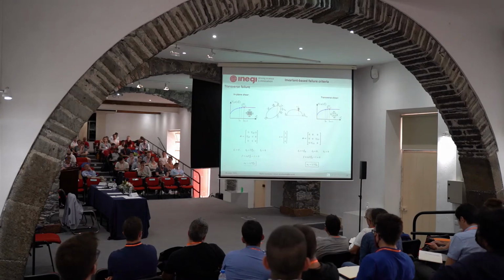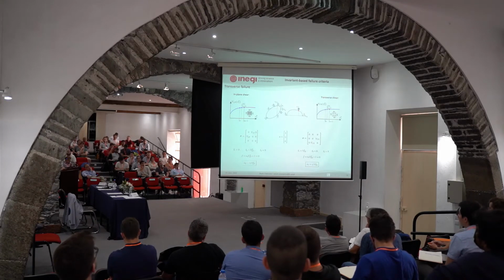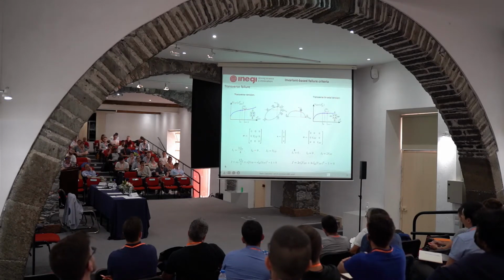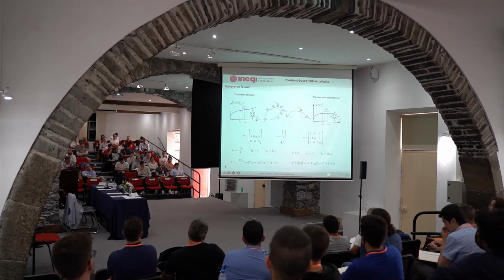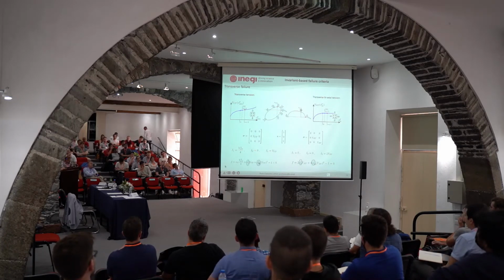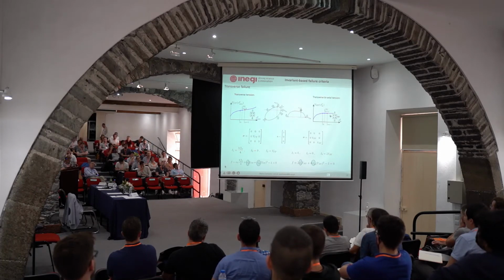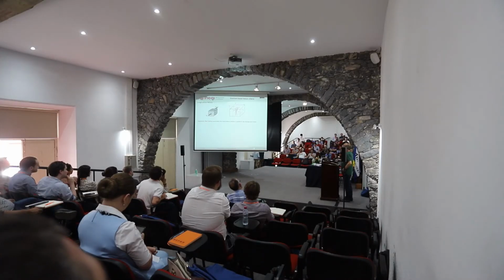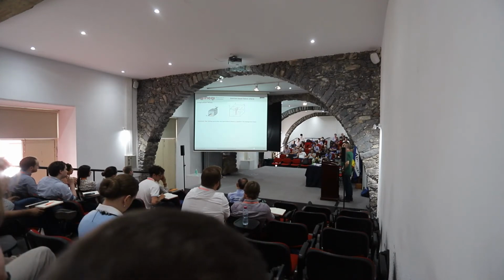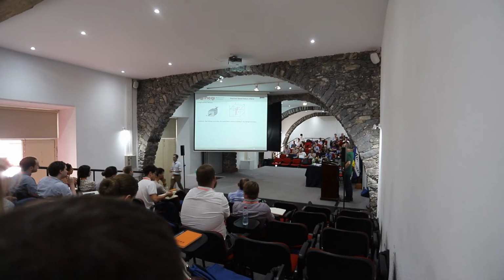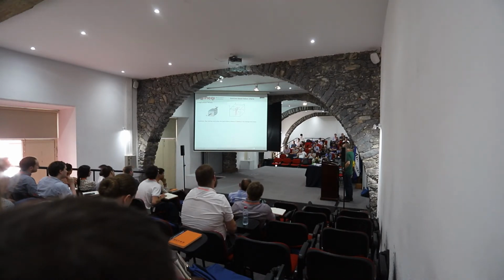But since it's a fully three-dimensional model, of course, we need more tests to obtain relevant material properties. So now in transverse tension, this is the stress tensor. Again, A is the same. And here I have two non-zero invariants. So when I apply the failure criterion, I have one equation and two unknowns. But if I apply now transverse biaxial tension, which is a complicated thing to apply, I can identify the remaining parameter. Now for longitudinal failure, which in my opinion is the most challenging failure mechanism to capture at this level of representation,